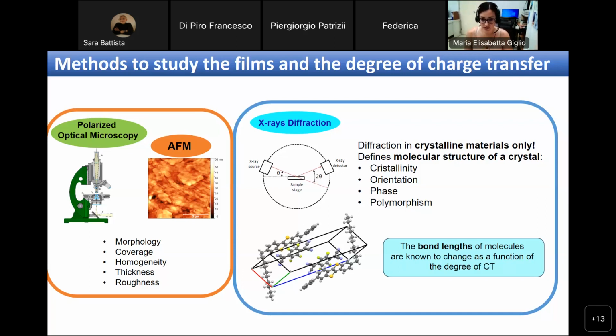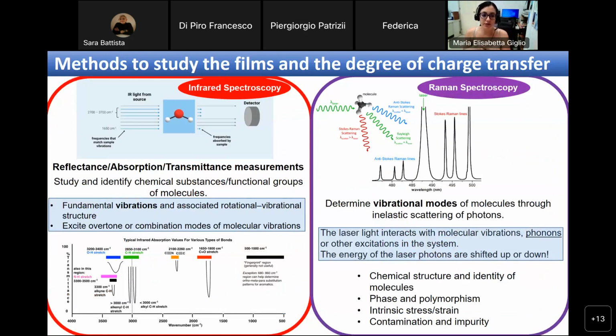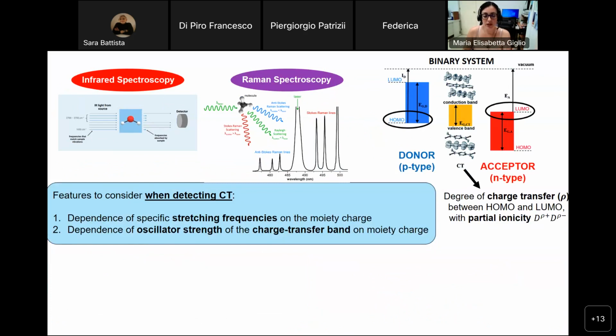So talking about CTCs, so charge transfer complexes, we know that the bond lengths of the molecules are known to change as a function of the degree of charge transfer. So this is also a first method in order to detect the presence of the charge transfer crystals. Then we perform infrared spectroscopy as well as Raman spectroscopy, which are fundamental techniques in order to determine the vibrational modes, as well as to study and identify the functional groups of the molecules, the chemical footprint of the molecules. And talking about CTCs, we exploit the dependence of some specific stretching frequencies as well as the oscillator strength of the charge transfer band on the moiety charge.